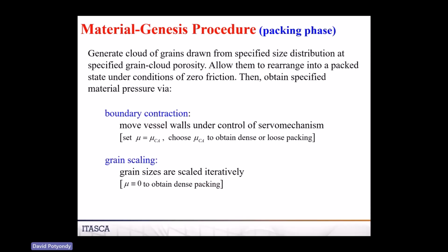It doesn't account for the overlaps. So when we were doing the 2D things, we were often using like 0.12. If we choose that porosity too high, then we just get a cloud of balls that are not packed. If we choose it super low, we get like incredibly high packed systems. Okay. So that's what you're going to specify. And then what they're going to do, the first thing is they're going to rearrange into a packed state with zero friction. Okay. So given them, you want to pack, they're going to get packed. They're going to get all packed tightly under zero friction. So they're going to be isotropically arranged because of that.